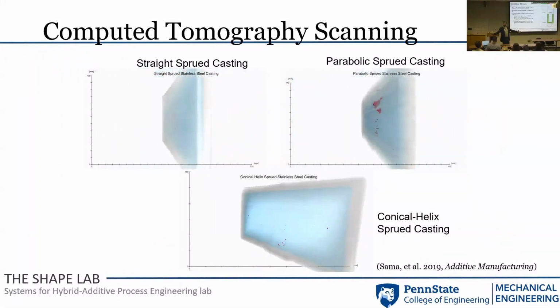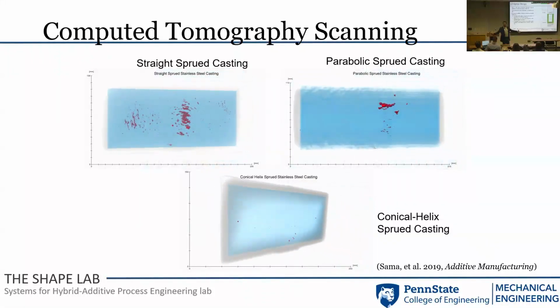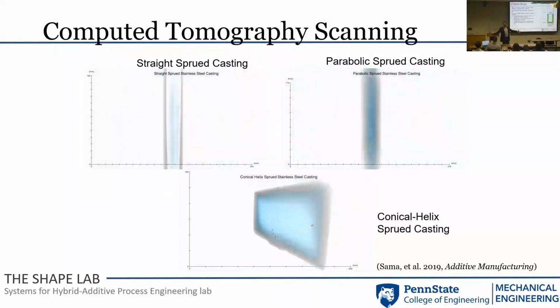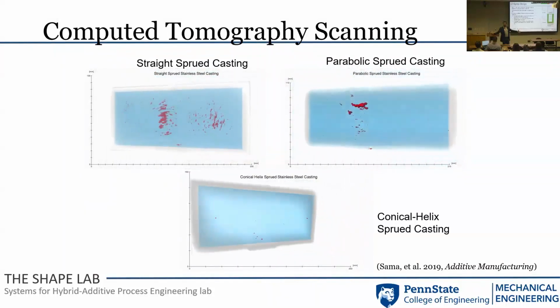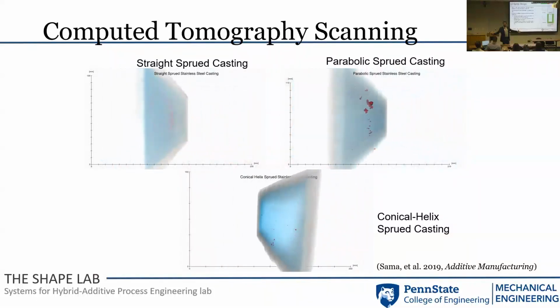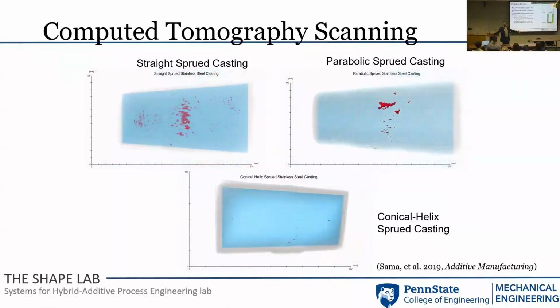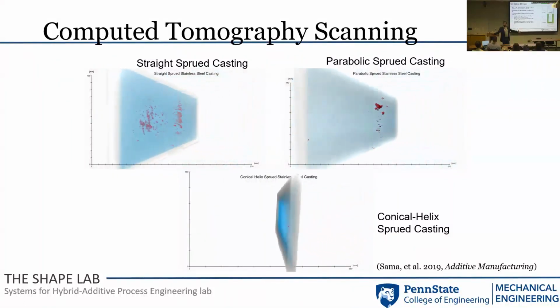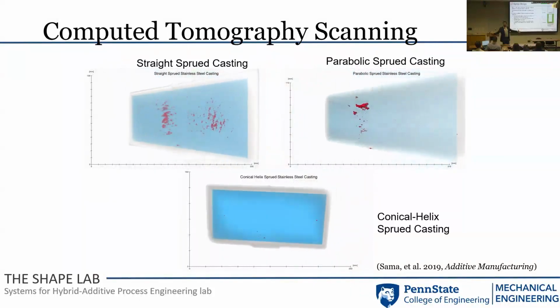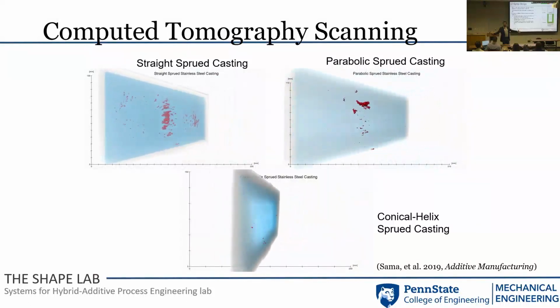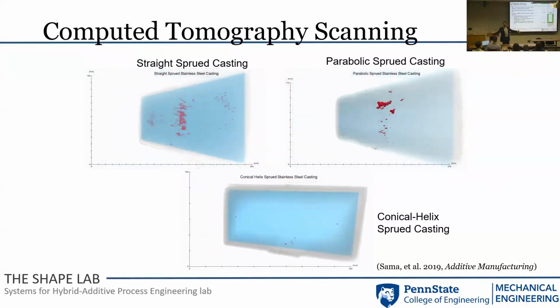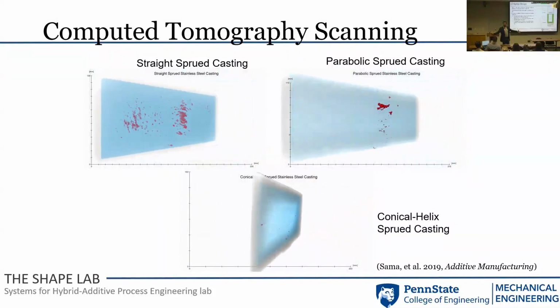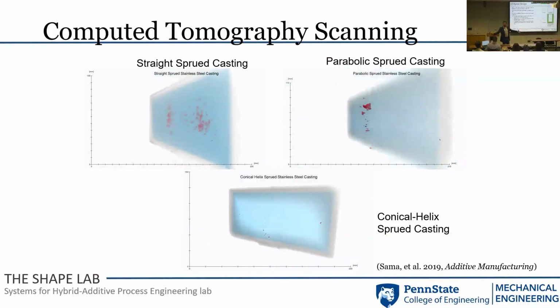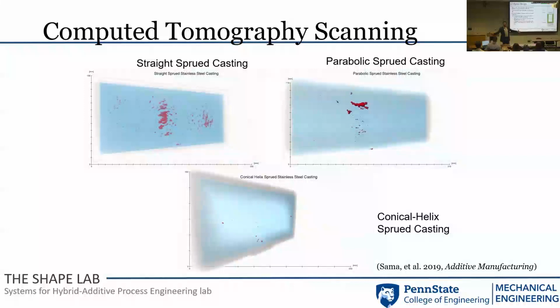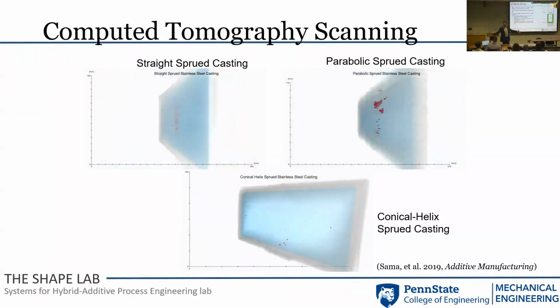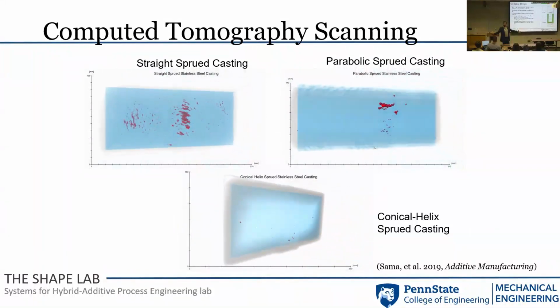The one saving grace with casting when compared to direct metal, and I make sure I put this in the first page of the proposal, is surface roughness: you cannot compare this with resolution with direct metal parts. And you cannot compare this with surface roughness of polishing either. I'm going to make an assumption that it's a sand cast part. You're going to get cast surface. You're going to remove at least 1/8 of an inch from the surface. So as long as I'm pushing my defects away to the surface, I'm kind of okay with it. So internally, oxides, trapped gas, trapped sand. And sometimes if you're using filters, I didn't show those. If you're using filters in your gate, sometimes if your filters don't have high temperature strength, some of them could end up getting broken up and it will be a nice big ceramic in the middle of a metal.